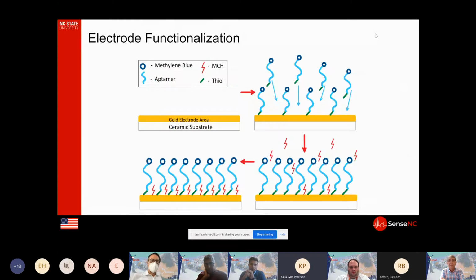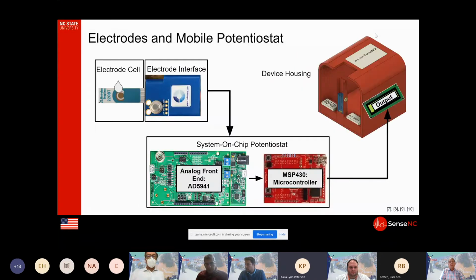Next, we procured the aptamer with a terminal thiol modification for attachment to gold electrodes, and the free end of the aptamer was modified with methylene blue as an electrochemical reporter. A self-assembled monolayer was formed on a gold electrode, and MCH was used to backfill the aptamer layer to reduce non-specific binding. Next, we designed an electrochemical system for transduction, utilizing a 3-electrode cell plugged into a custom portable potentiostat that runs square wave voltammetry. We integrated a system-on-chip potentiostat, an IR temperature sensor, and a microcontroller, with results presented onto an LCD screen. Benchtop testing was used to create a database of calibration values, which correlates concentration to current peak magnitude. Thus, results can be output as quantitative viral load concentrations or qualitative diagnoses.